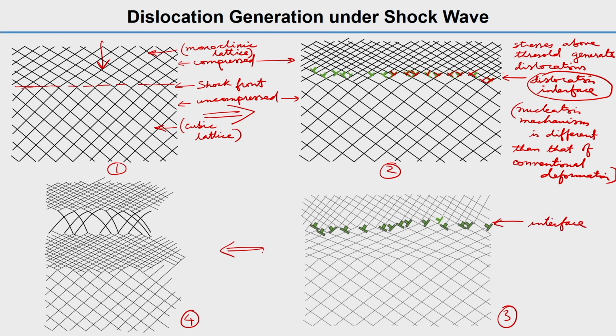interface we have, and then the shock wave, the shock front, will advance, that will be ahead now, ahead of the interface. So what happens is, these are some dislocations, we are not showing the dislocations. There is a dislocation interface here, there is a dislocation interface here, there is a dislocation interface here. So what will happen when the stresses at this point